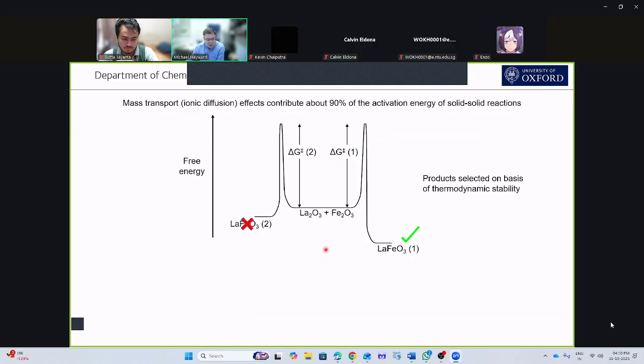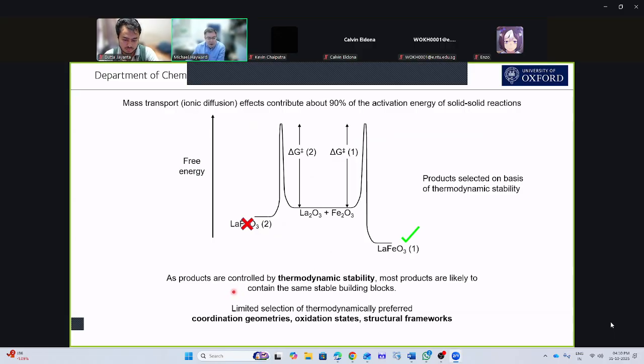And unfortunately, the situation is even worse than that, because if the products of these reactions are thermodynamically controlled, so if their thermodynamic stability is the key feature, what we'll find is that they'll be made up of the same building blocks, because thermodynamically there are preferred coordination geometries for our transition metals, there are preferred oxidation states, and preferred structural frameworks. And so what we find is for any one composition, I can only make one thing, the most stable compound, the most stable phase. And unfortunately, the stable phases I can make all look quite similar. So this is a bit of a problem in solid state synthesis.